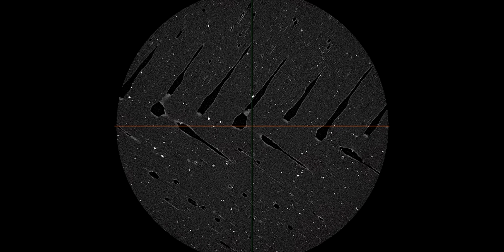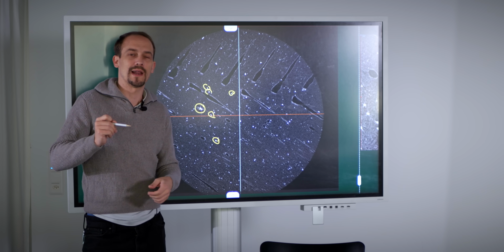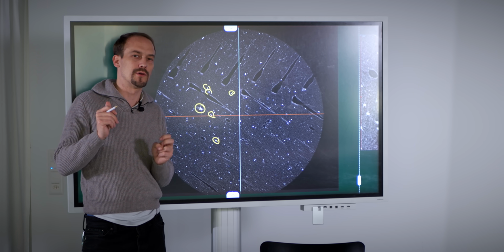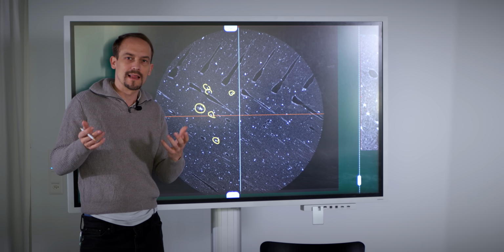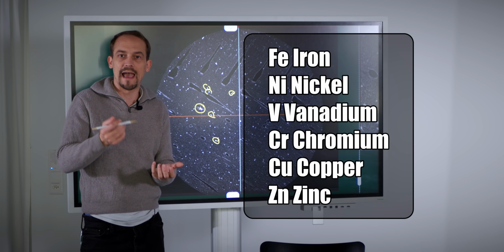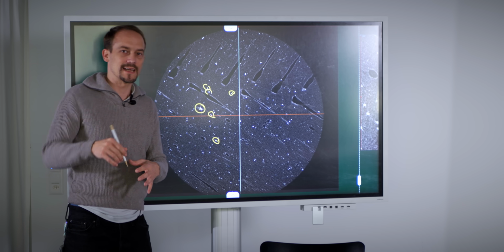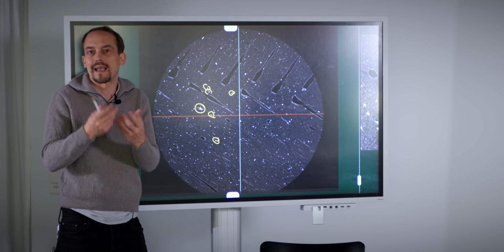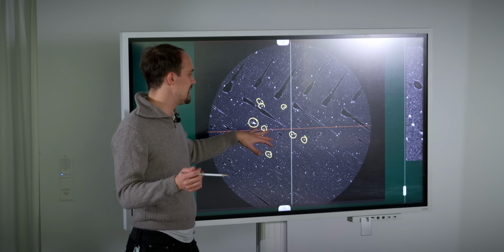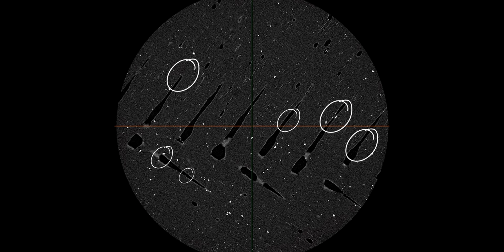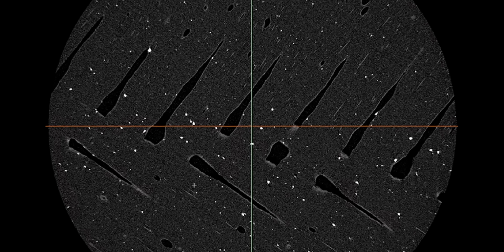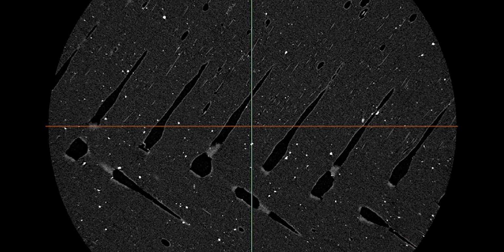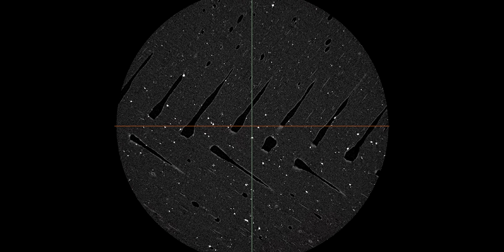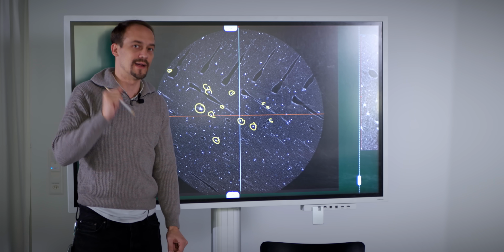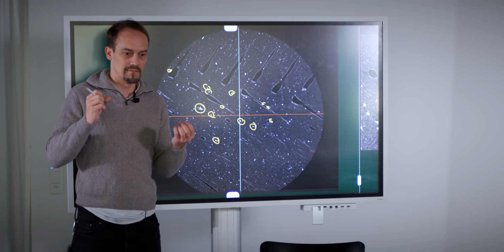So I looked a little bit deeper into it, and that is actually carbon black. This is because the carbon black is made in a furnace, and while doing that you get impurities, and that can be nickel or even metal, like Fe, inside of the compound. Carbon black is actually used to make filament black. So that means this is a little bit more abrasive. So even though they put the carbon fiber in the middle of the strand to protect your nozzle from wear and tear, those carbon black particles are sometimes on the edge of the extrusion, so they will touch your nozzle. And they are hard and they are abrasive. It's basically like printing sandpaper.